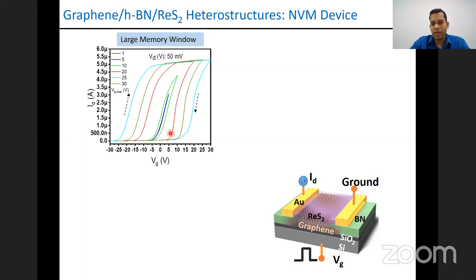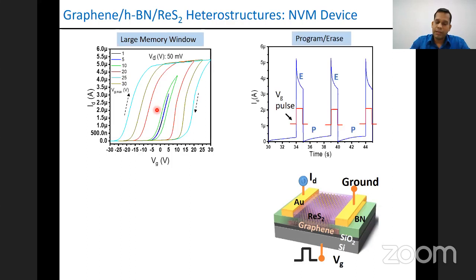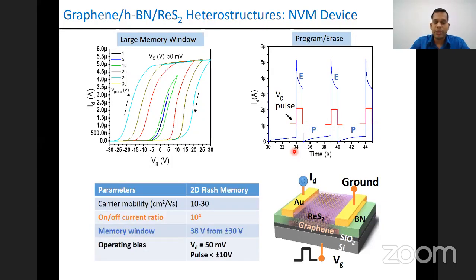And if we change the gate field strength, then we can reduce the hysteresis and decrease the memory window. We can again do multiple pulses, and we can do the erase and programming process multiple times. So that also gives the reproducibility of the program and erase step. And various parameters I mentioned here. So we have an on-off current ratio that can be high, like 10^4, with a large memory window, and also a low operating bias, like 50 millivolt with a pulse of plus minus 10 volt.